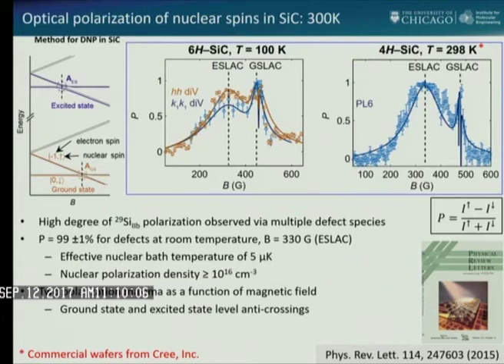And just to emphasize what a big effect this is, to get this type of effect in a material, you would normally have to be at microkelvin temperatures to get these sorts of polarization states. So this is a very, very efficient effect. And it's because at the right magnetic fields, the Zeeman crossings between the electron and the nuclear spin overlap, and you get very efficient exchange. These polarized electrons, that are 100% polarized, flip their spins by flipping a nearby nuclei. They just exchange information. And they do it very efficiently at these fields, which are these fields.